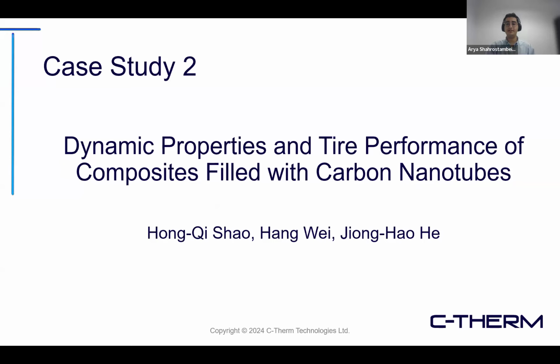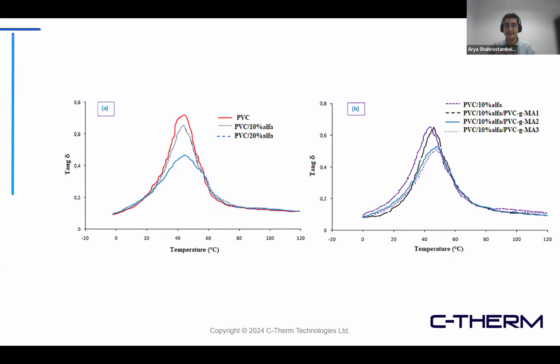Another important part here on the right-hand side, again tan delta, is that you can easily see that the temperature of glass transition has changed. By adding more of your compatibilizer number 3, Ma3, the glass transition temperature has shifted higher. It means that your material becomes stiffer. And in contrast, by not adding or adding Ma1, you see that the glass transition temperature has actually shifted to the left, or your material has become softer.